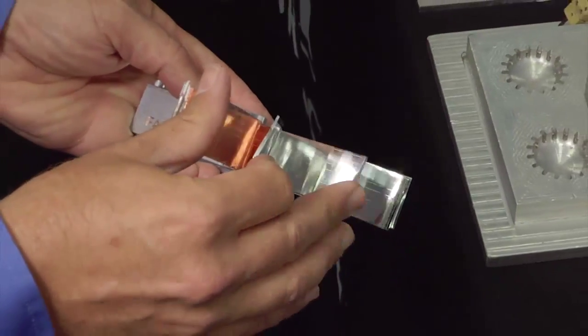So this part never saw above, say, 200F. From a metallurgy standpoint — I'm a metallurgist — when you don't heat up a metal, you don't wipe out all the properties that you try and get from the mill. So we're able to get much better metallurgical properties right out of the box.